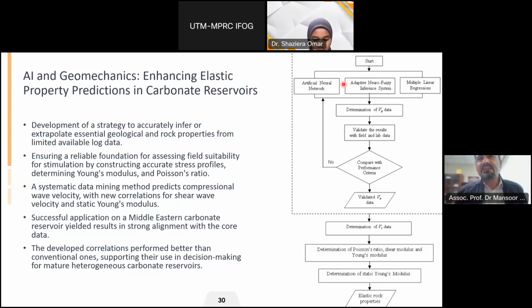As you can see, we use three methods in coming up with VP, or compressional and shear data. After that, we validate the results with leak-off test data and lab or UCS data, and then we compare the results. VP was validated by one well log, and then we come up with the VS, or shear data, based on the VP data. Based on the current correlations, we determine the Poisson's ratio, shear modulus, and Young's modulus. Of course, these are dynamic data, so we need to turn them into static Young's modulus. Finally, rock elastic properties are achieved, and we've been able to come up with stress profiling and then the design of experiments.